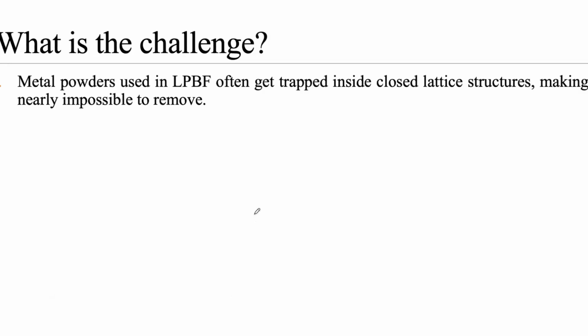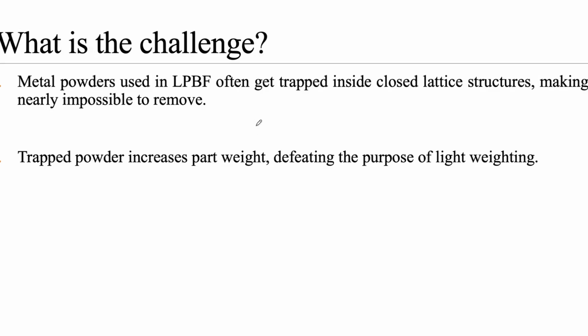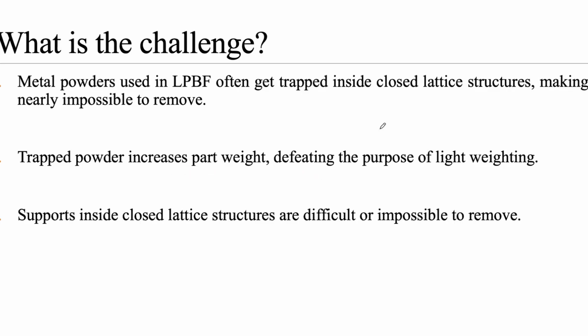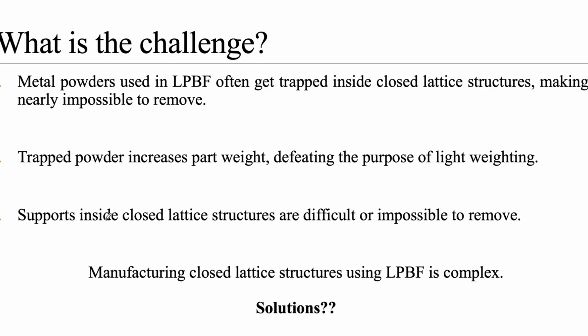The challenge is that the metal powder which we use in laser powder bed fusion gets trapped inside these closed lattice structures. Because the structure is closed from both ends, there is no provision for removing those metal powders. And if the powder gets trapped inside the structure, it increases the overall part weight, which entirely defeats the purpose of lightweightedness. So this is one problem. Another problem you will probably face is that if you have some kind of support structures inside a closed lattice structure, they are also very difficult or impossible to remove. So manufacturing closed lattice structures using laser powder bed fusion is very complicated.